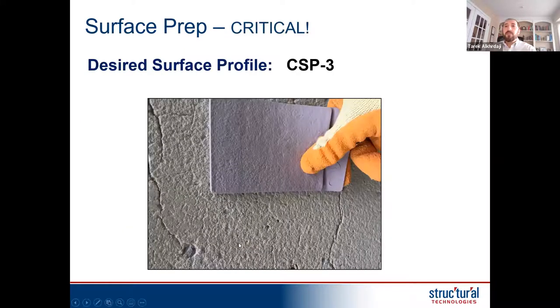So this is the surface of the concrete, and any concrete, no matter how good it looks, once you sand it or sandblast it, it's going to end up like this. You can find all kinds of micro cracks that you typically don't see by eye. And that is normal, right? Because we design reinforced concrete, as an example, in which the steel reinforcement is not going to be engaged in tension until it gets some micro cracks in the concrete, as part of the behavior we designed for.